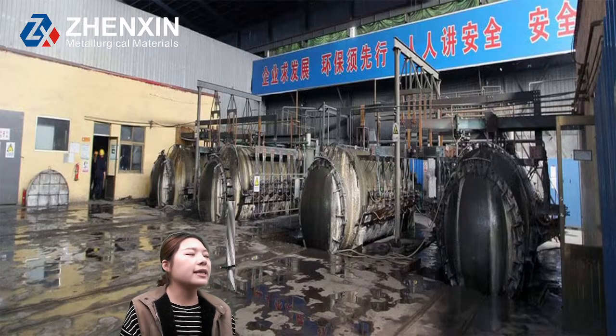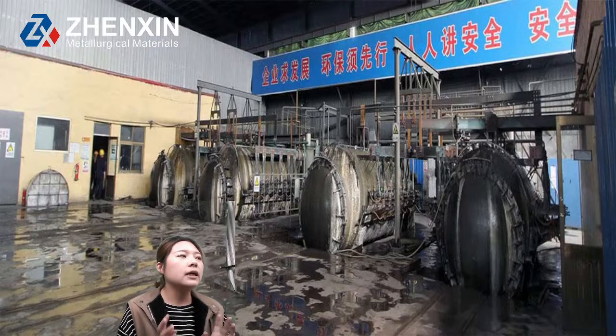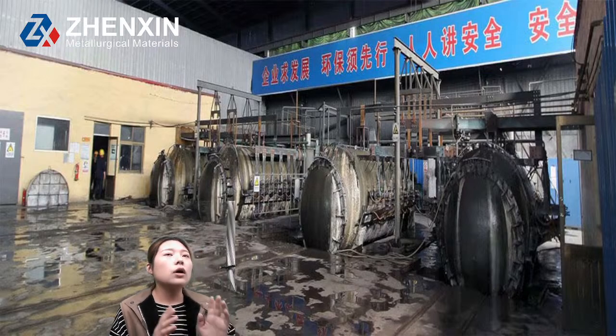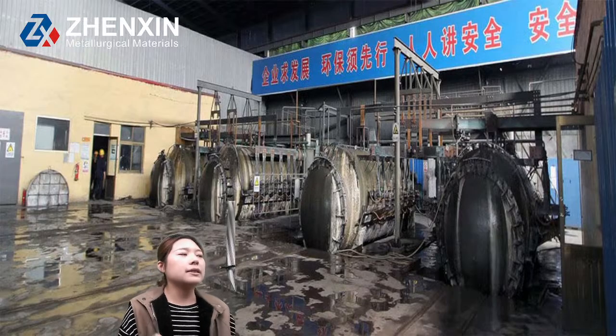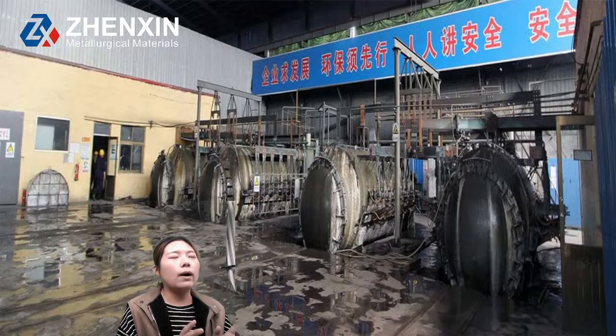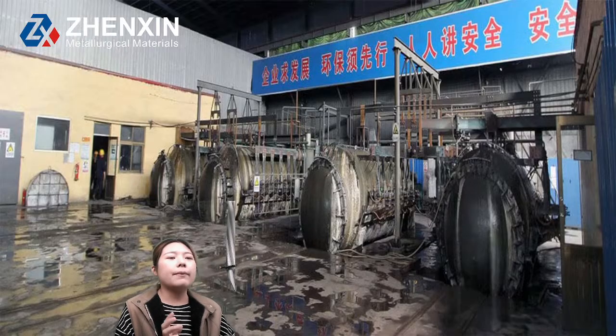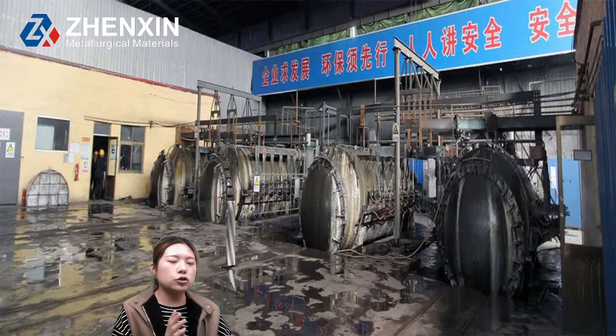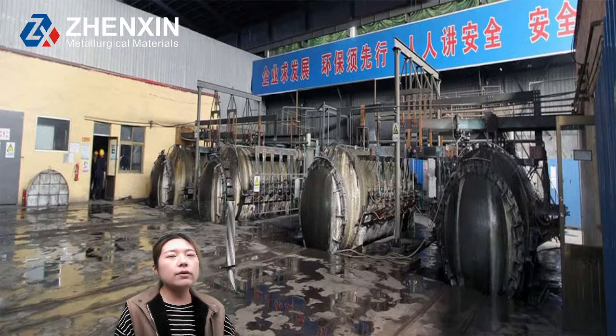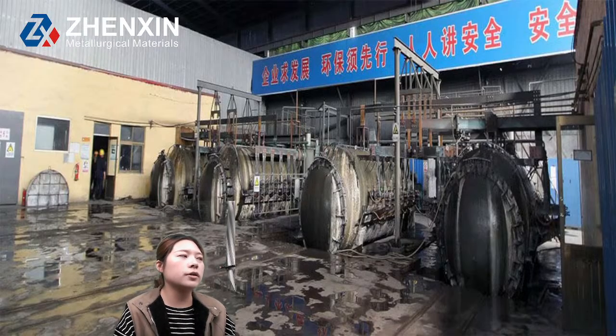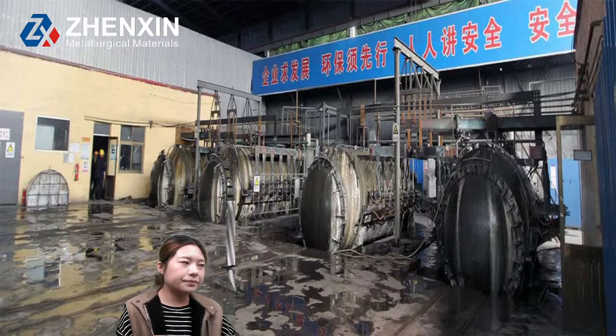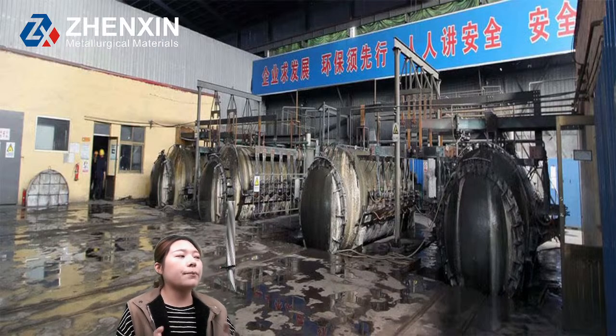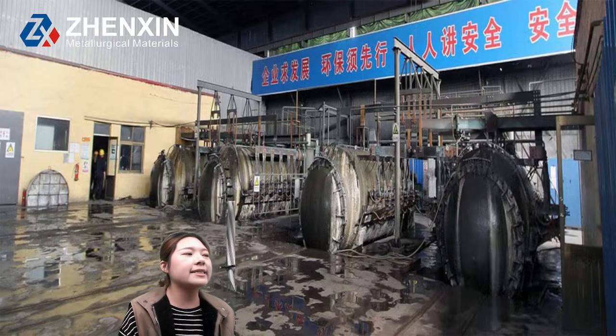Yes, about ferrosilicon 72, the silicon content is 72 to 75%. Yes, and the aluminum is 1.5% maximum or 2% maximum. Yes, the carbon is 0.2% maximum. And we also have the low specification, low silicon ferrosilicon 65%, with silicon around 65%, often used in certain casting processes.